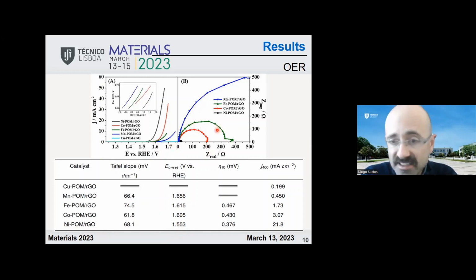this impedance data. So these are the Nyquist plots that show the electrochemical impedance spectroscopy analysis, and we have much lower impedance here for the nickel POM. So the charge transfer resistance is given by the diameter of this semicircle, and as you can see, it is much lower for the nickel POM and then followed by the cobalt POM. So these were the most interesting materials for oxygen evolution reaction.